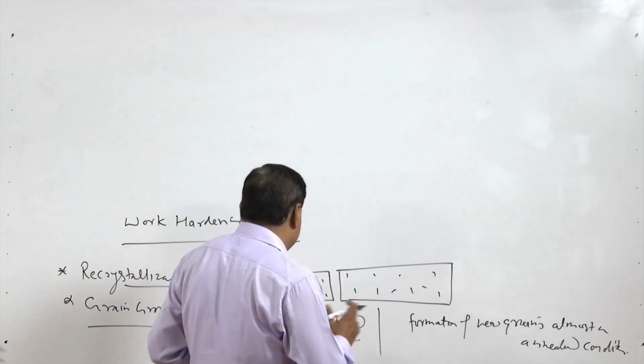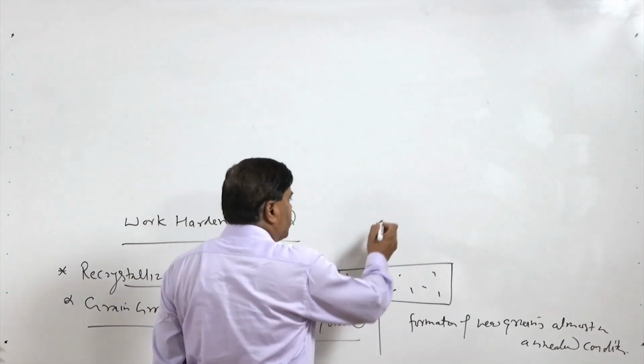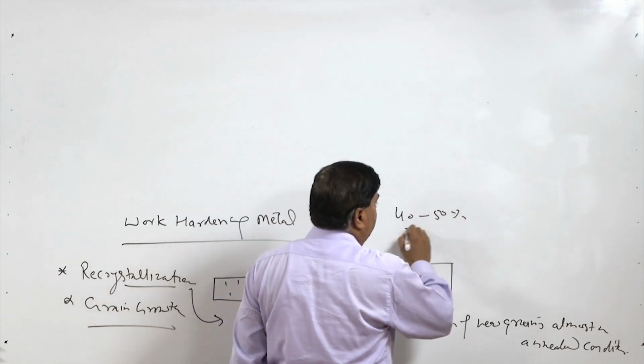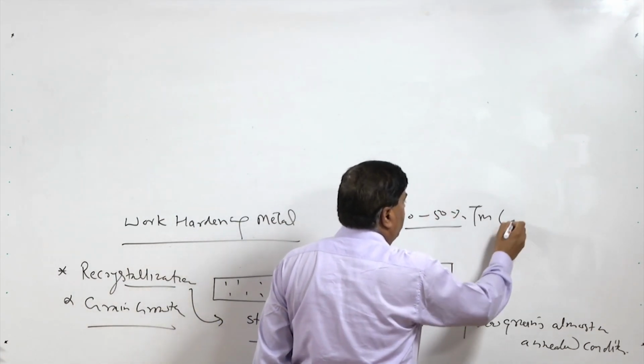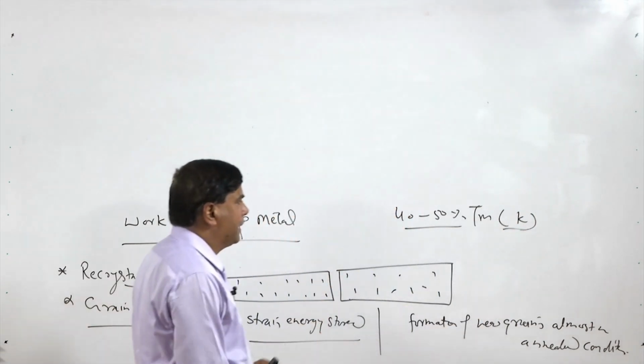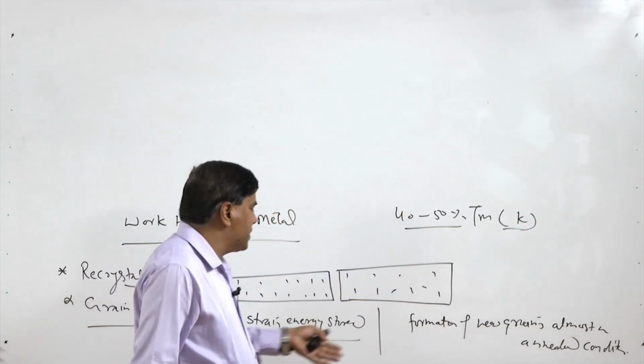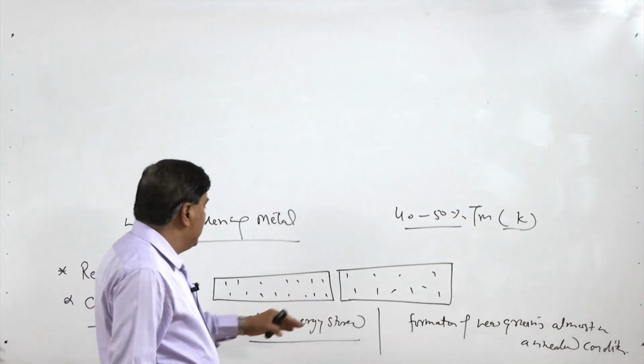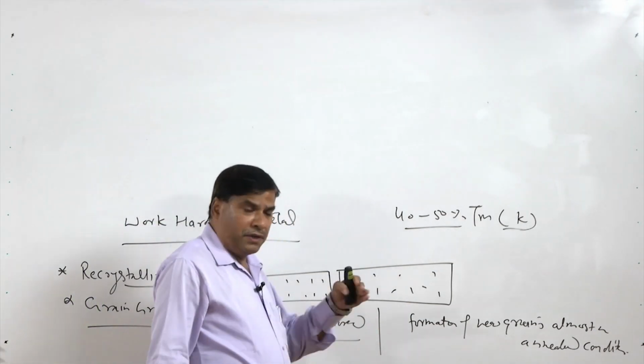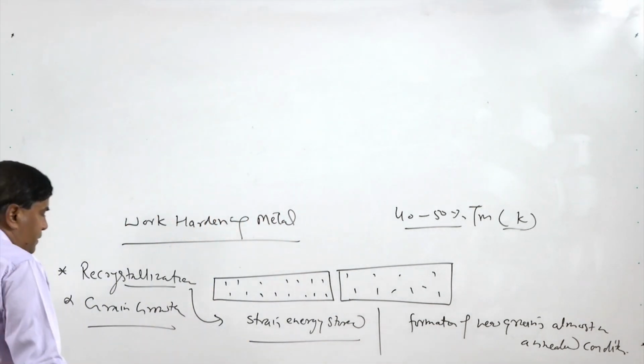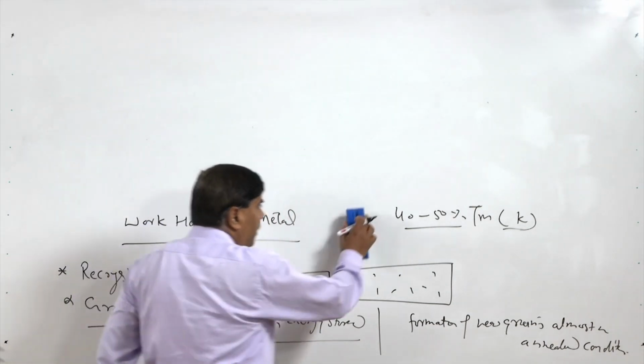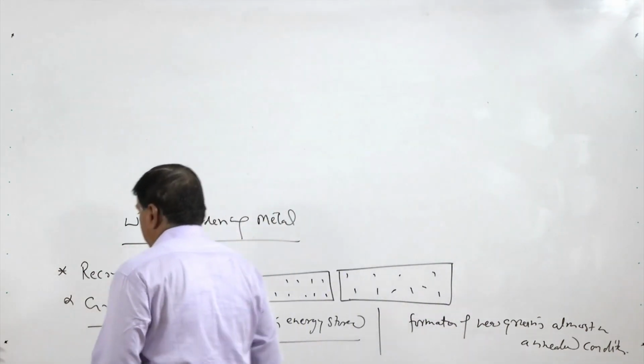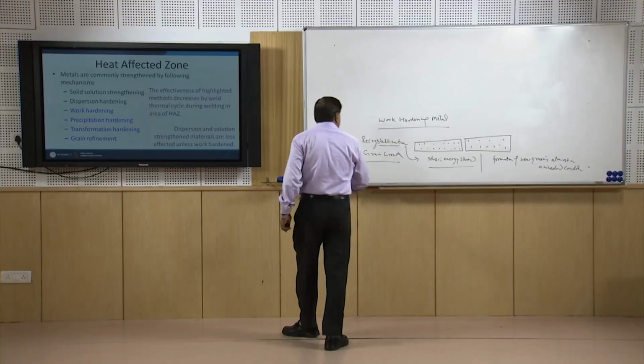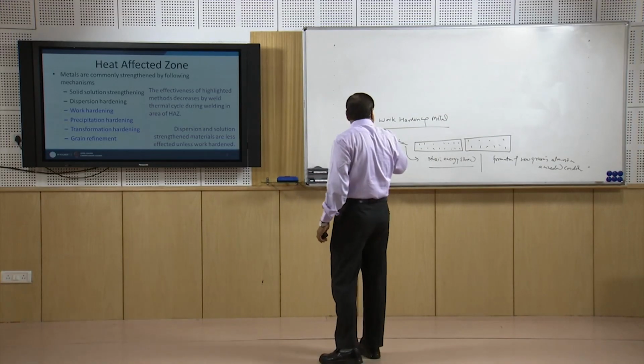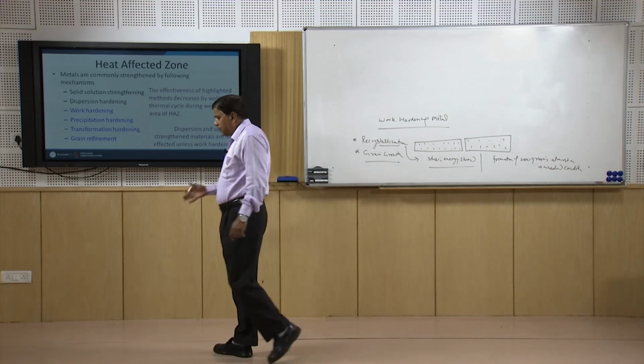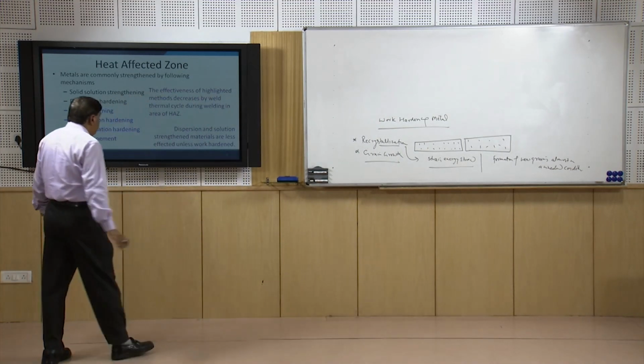So, the formation of the new grains happens at a particular temperature, like say 40 to 50% of the melting point temperature in Kelvin of the given metal, and this temperature sometimes decreases with the increase in the strain energy stored or due to the kind of deformation to which the material has been subjected. So, what we will see here is that the strain energy stored affects the temperature at which the recrystallization will be occurring.